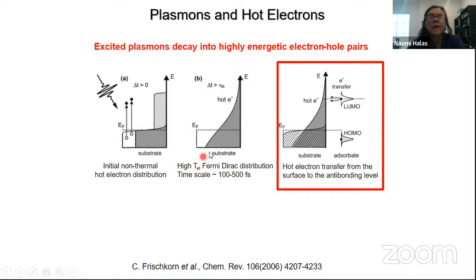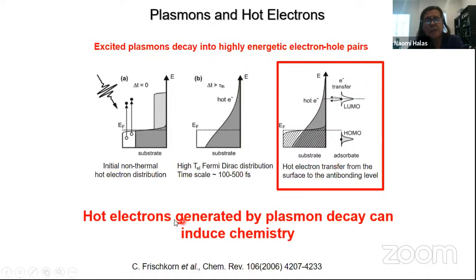This non-equilibrium population is relatively short-lived, but it's long-lived enough that if I have a molecule sitting on the surface of that nanoparticle, then I can actually have charge transfer from, for example, the hot electron population to an unoccupied molecular orbital just outside the surface. The relationship between the electrons inside the metal and the adsorbate outside and its ability to interact with the substrate allows us, by, for example, tunneling processes, to create hot electron processes, and we can also create hot hole processes, and both of those can lead to a chemical transformation of that adsorbate molecule. So the basic theme is if I can make hot electrons, generated just by plasmon decay, then they can actually induce chemistry.